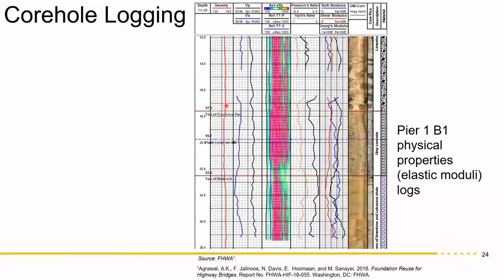Also, we have a different tool we call a compensated density tool that gives you calibrated density measurements. Now, if you have velocity and density measurements, then you have all the elastic moduli information. And so doing, you can get the Poisson ratio as the black curve shown here, as well as Young's modulus, shear modulus, and bulk modulus. So you can get all the modulus information continuously every inch from the top of the core holes down to the bedrock. Here was the moduli information for the concrete pad.